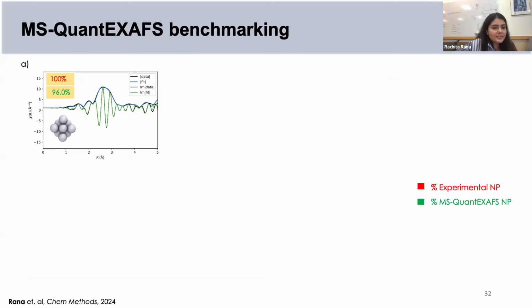The first one, what you see, is a pure nanoparticle of platinum on magnesium oxide. There was no isolated platinum. What you see in red here is the experimental fraction of nanoparticle that was mixed in the sample, and what you see in green is the predicted value of that fractional contribution using MS-QuantEXAFS. We did different reproducibility tests, and what we found was fairly decent agreement with the targeted fraction of nanoparticles versus atomically dispersed platinum in each of these systems.